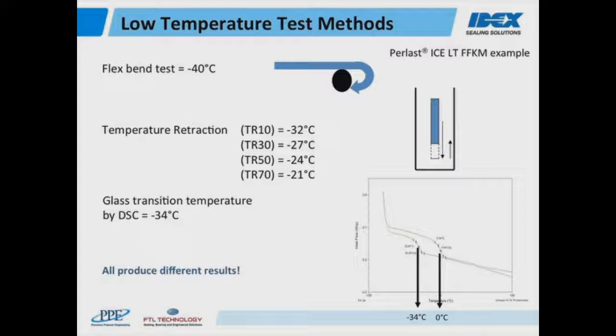The main point is that there is some variation in the test methods and the results, so we should look for large differences among materials to guarantee the seal will function at very low temperatures. A few degrees of difference among various materials is not likely to bring big benefits in where the seal can be used.